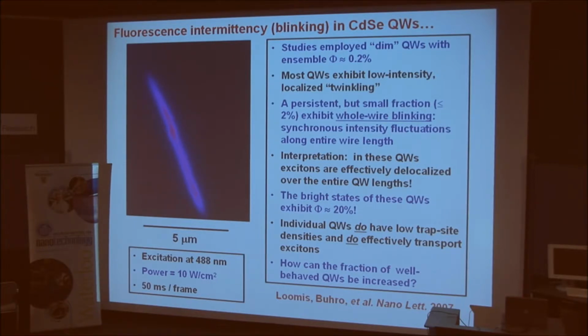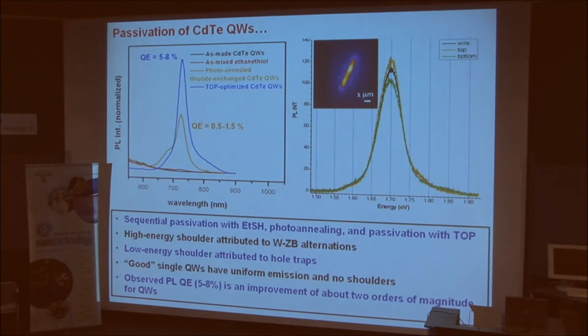Well, we can't quite answer that question yet, but let me show you in another system. This is cadmium telluride now, where with various surface passivation schemes, we can dramatically improve the bulk photoluminescence efficiencies of our specimens. These are the photoluminescence spectra of cadmium telluride quantum wires, and this black trace is the PL spectrum as synthesized, when the cadmium telluride wires are first obtained from the synthesis. You can see there's no PL.